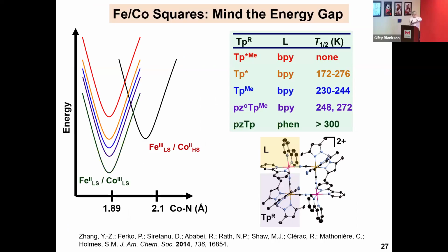All right, so showing you just some metal ligand trends. There's a Goldilocks zone in all of this, in that if you have a very good donor on iron and a moderate donor on cobalt, you don't see any electron transfer. In other words, you're trapped in that state. Can't reduce the iron further. It has too much electron density. When you remove some electron density from the iron at the aryl borate sites, keeping the ligands on the cobalt fixed, now you start to see electron transfer. Now they're close enough in energy that you can access it by temperature change.